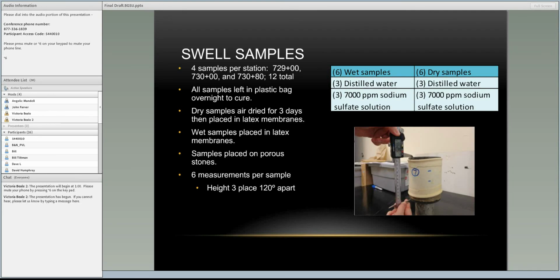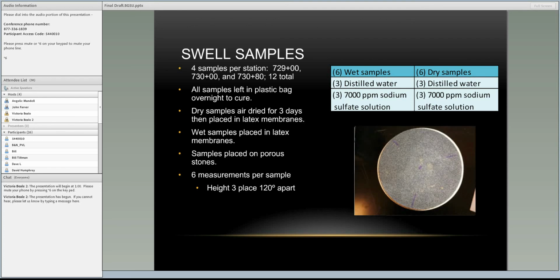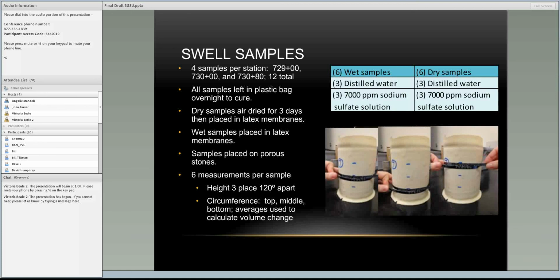And here's the results. So we found it made better sense, or it was easier to look at, by separating out the wet samples from the dry samples. And as you can see here, 730 swelled the most, both in the wet and the dry samples, followed by soil from station 729, and then soil from 730 plus 80.